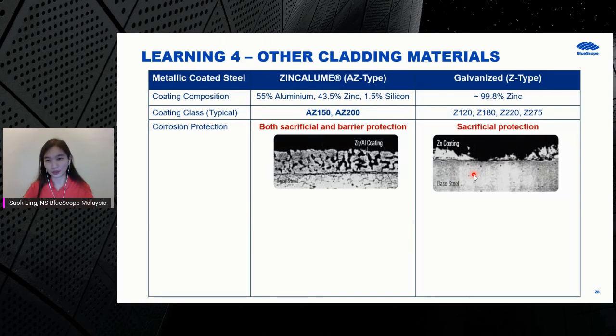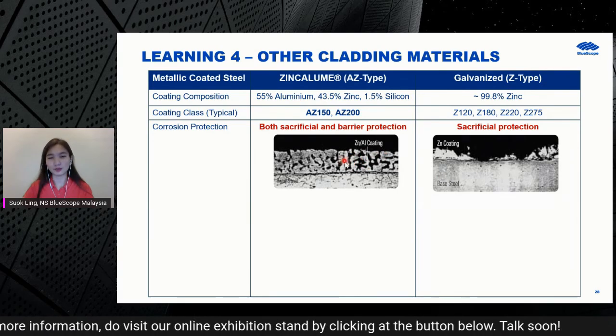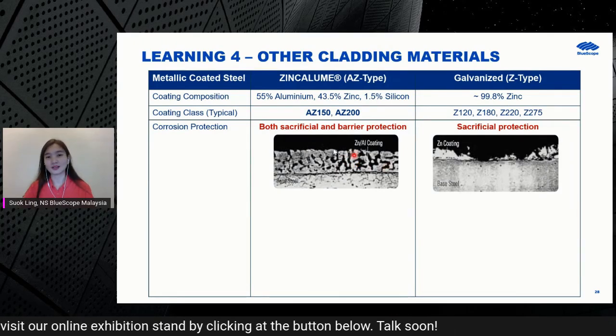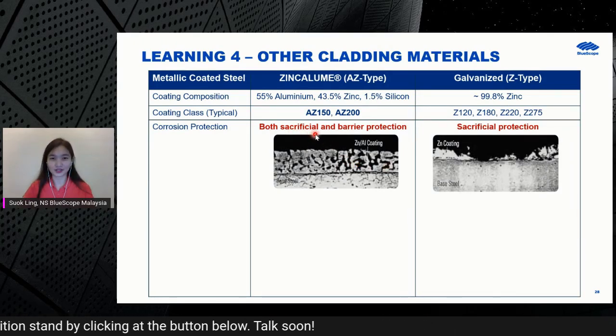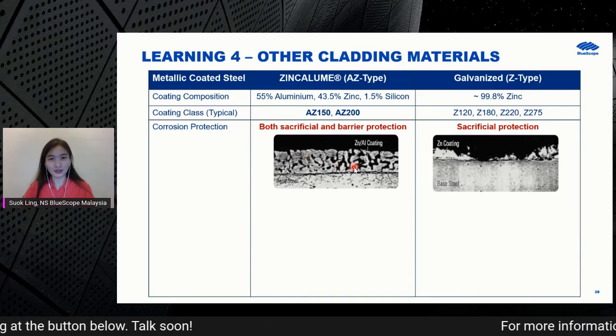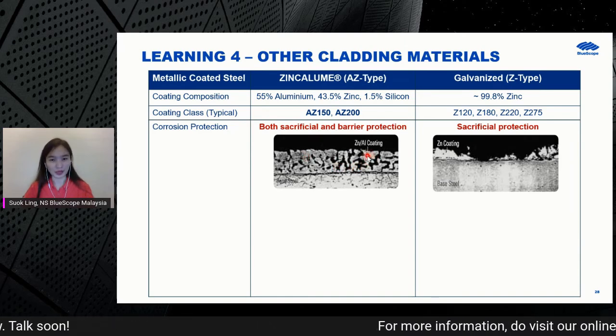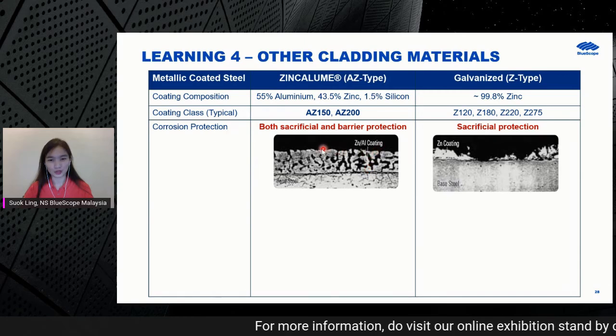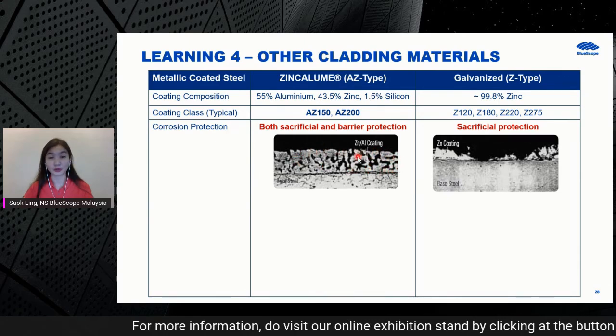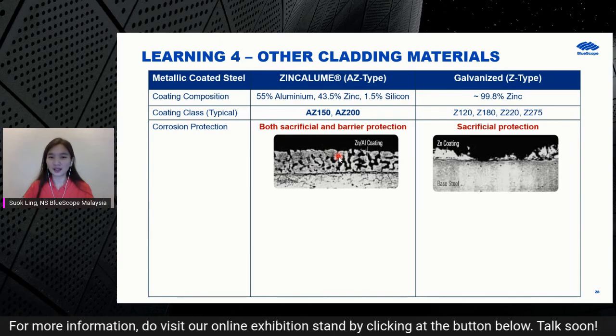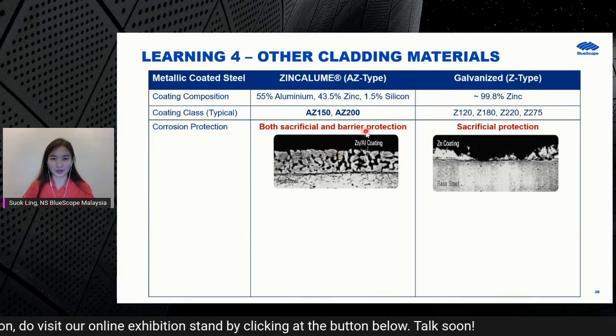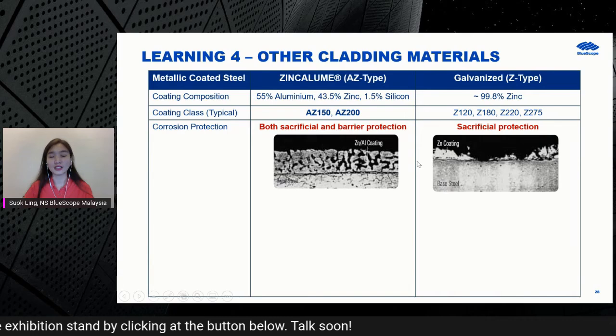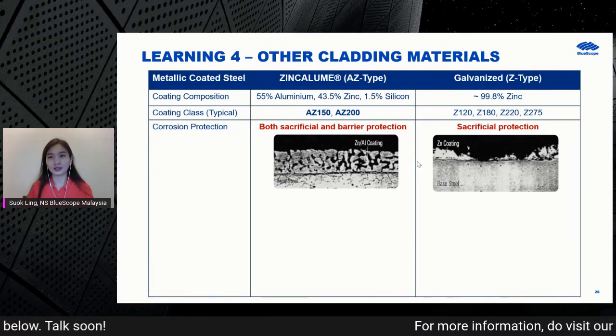corrosion to happen afterward. For Z type, the black spot over here is actually the zinc content which has already been oxidized, because the zinc will still act as a sacrificial protection. But for AZ type, it still has the remainder of aluminum, which are those gray colors, which still act as a barrier protection. That's the reason why, in terms of corrosion resistance performance, AZ type tends to perform better compared to Z type.